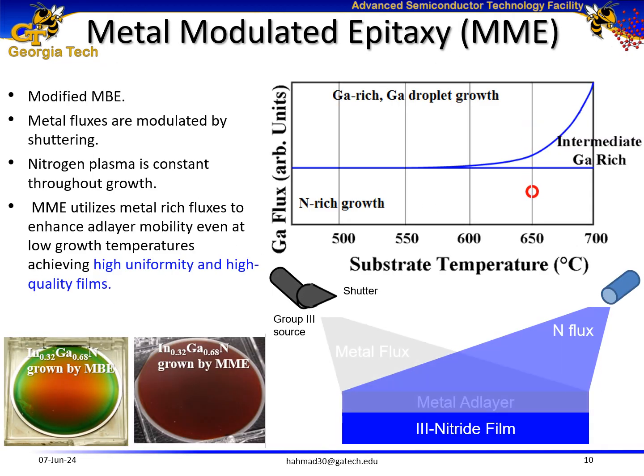Metal modulated epitaxy is a modified MBE growth technique in which the metal fluxes are shuttered while keeping the nitrogen flux constant. It utilizes metal-rich fluxes to enhance metal adatom mobility at low growth temperatures, achieving high uniformity and high quality films as compared to typical MBE.